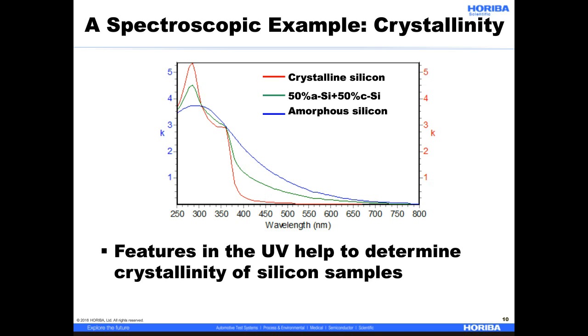If you look at the red curve for crystalline silicon, you end up seeing that the peaks are typically very sharp. As the material becomes amorphous, you start to see a broadening of the peaks. If you look at the green curve, it's somewhere in between the crystalline and the amorphous, which it is—it's a 50-50 mix. So features in the UV are helpful to determine crystallinity of your samples.